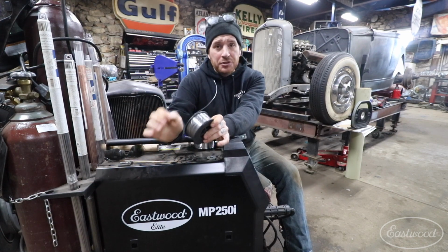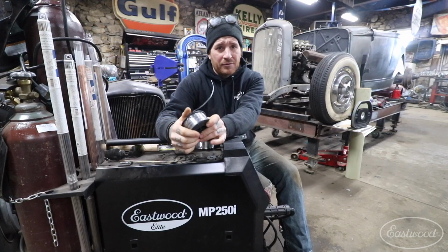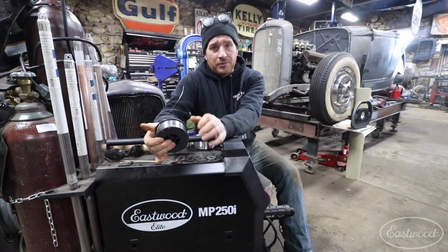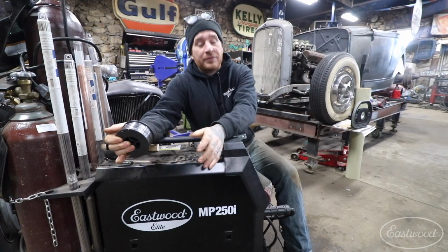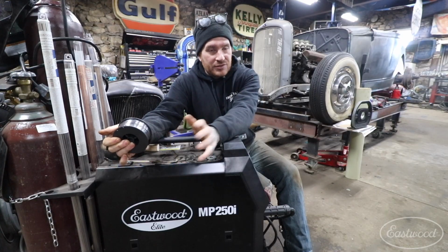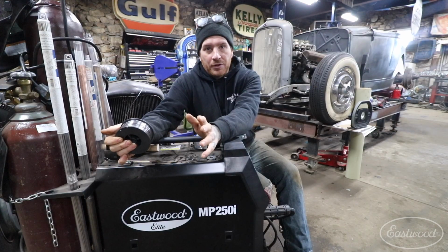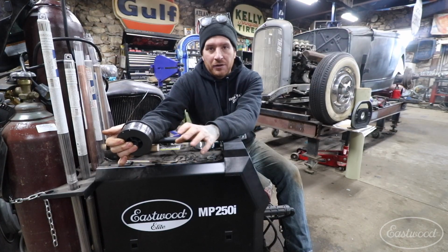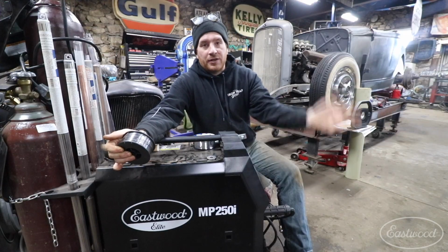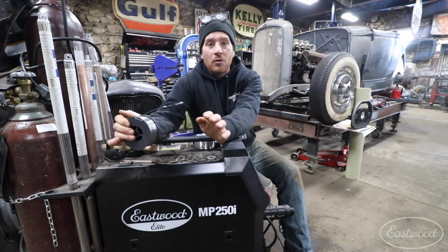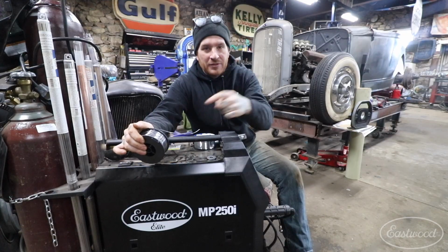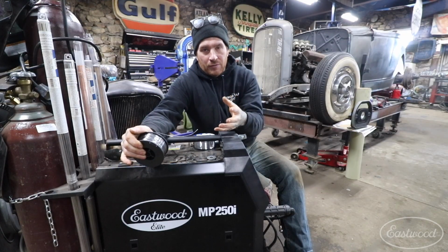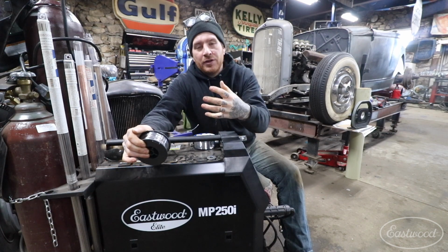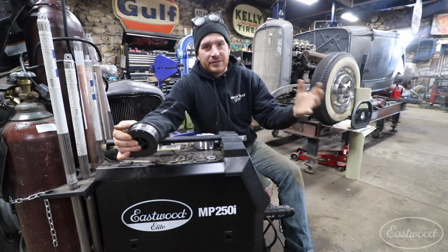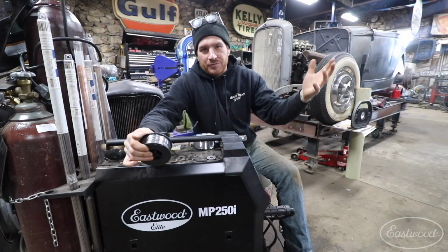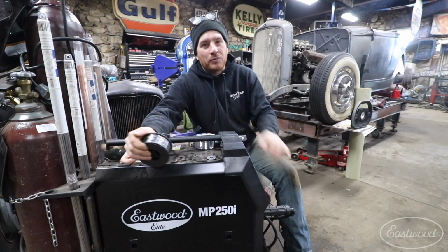It is true, if you look online, you've probably read or heard of people saying you can weld stainless steel with a mild steel wire like the ER70S. You can weld the two together and it will fuse the metal and work, if you're trying to weld, say, a stainless exhaust using that mild wire. What does happen though is your weld seam is going to rust, and it's going to rust out at that point. The reason for using stainless steel is that it doesn't corrode, and you negate that property by welding with mild steel wire.